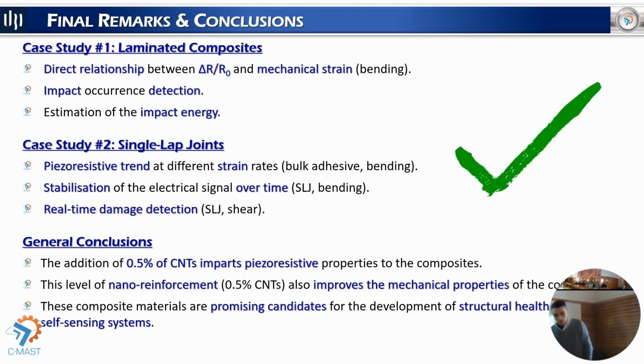To conclude, some final remarks and conclusions. First, in the first case study, the laminated composites, we observed that there was a good relationship between the relative electrical resistance variation and the mechanical strain in the bending mode. And we also observed that we can detect the occurrence of an impact event, and at the same time we can have an idea and estimate the energy that was involved in this impact.